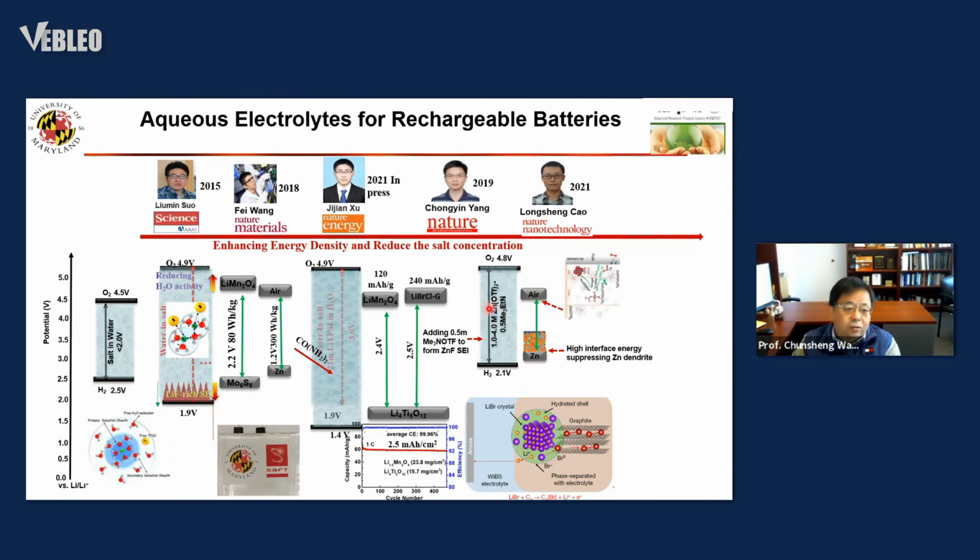The air cathode uses the exact same principle as water in salt. While we have a high potential, the TFSI or OTF ion is hydrophobic. They can block the water on the surface, and so they can avoid water oxidation. Water is not involved, and then the oxygen redox changes from 4 electrons to 2 electrons. Then the reaction is very fast.